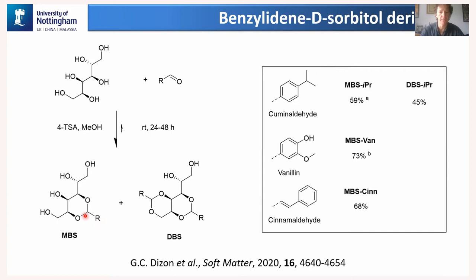You can see in this case, there's one aldehyde which has reacted with the sorbitol derivative, and we'll call that MBS, that's monobenzylidene sorbitol. And then just on the right here, you can see that there have been two reacted. So it's reacting with these two hydroxyl groups here in this case, and that's giving you another derivative coming off the side here, this R group again, and that's the dibenzylidene sorbitol derivative. So Dizon took different aldehydes with sorbitol.